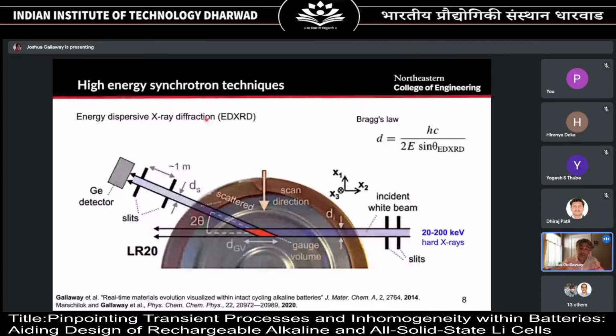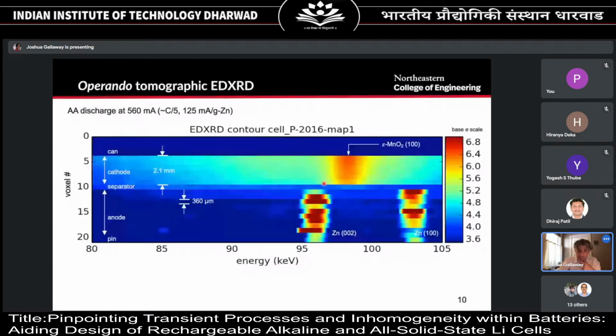And this data was taken while the battery was being discharged. So here we see the two biggest reflections of zinc in the anode, and this is the biggest reflection of MnO2 in the cathode. And as I discharge the battery, here's what happens. In the anode, I see two more reflections start to form against the separator, and they're propagating backward into the anode bulk. So that shows me exactly where the anode discharge reaction is happening. It begins at the separator and then starts to happen further away from the separator.